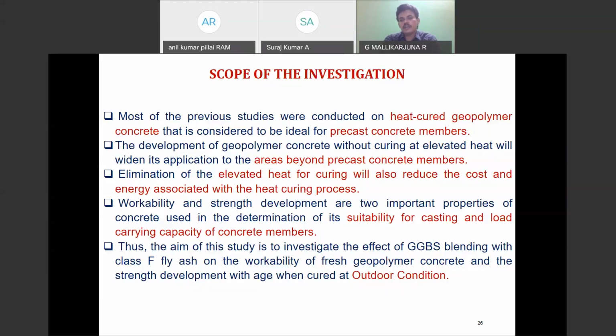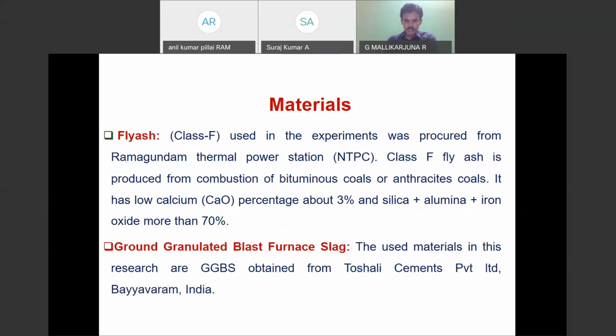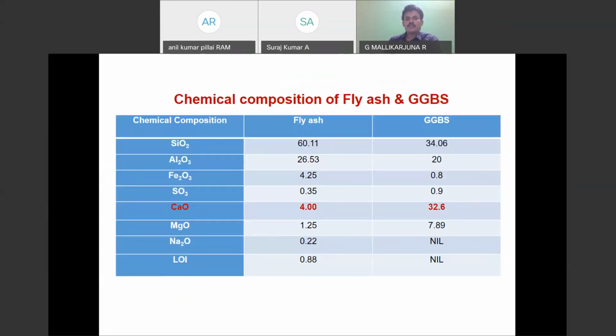In order to overcome that limitation, since there are no proper guidelines for it, we took different combinations of this fly ash and GGBS and developed one mix design methodology for the geopolymer. We collected the fly ash from NTPC Ramagundam, and the ground granulated blast furnace slag from Toshali Cements Pvt Ltd, Bayyavaram, India. This is the chemical composition of the fly ash and GGBS, and the calcium content present in the GGBS is approximately 32.6%.